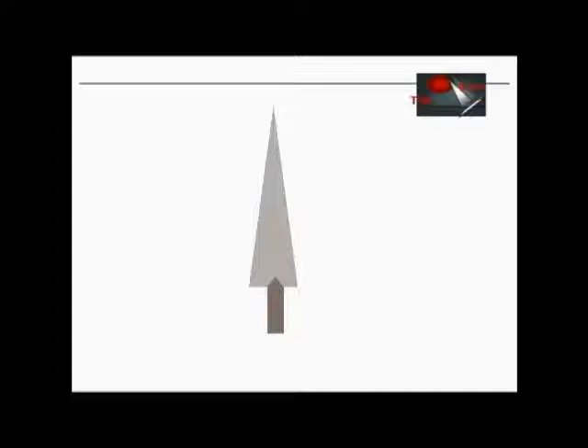Don't even try to find a reason to do it, except you don't want to use this blade and hang it at the wall. In this case I would rather go with a forged sword because it will be stronger than the welded one. Through the heat of the welding process and the high carbon content in the blade we get a brittle layer between the weld and the attached material. Since welding is done through excessive local heating, the heat is drawn very fast into the surrounding cold metal. You distort the whole lattice of the steel grid. And worse, you create a brittle layer where you want to attach the pieces.